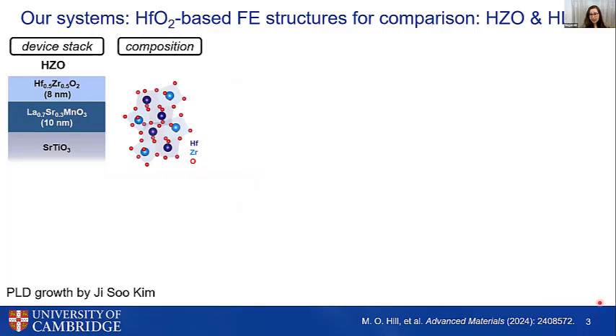So to do this, we designed two sample systems that we could use to better compare and try to decouple some of these effects. The first one is our reference sample, which is a hafnia zirconate stack, which is the most traditional hafnia ferroelectric. It's grown to an 8 nanometer thickness on lanthanum strontium manganate on top of strontium titanate. And this is grown using pulsed laser deposition.